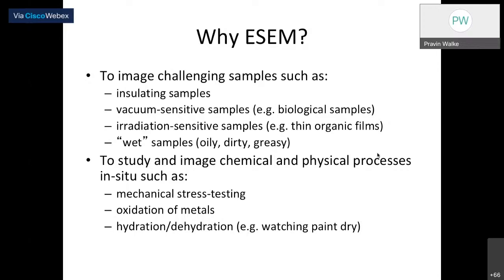ESEM is important to image challenging samples, for example, insulating samples, right? It's very difficult to get an image from an insulating sample as we are passing the electron beam. If we have an insulating sample, then the electrons will not go towards the ground, and a lot of electrons will stay on the surface, and charging effects happen on the image. Because of the charging effect, it's very difficult for us to see the topography or capture the image, because the beam will not stay steady on the surface and it will start deflecting on the sample surface.